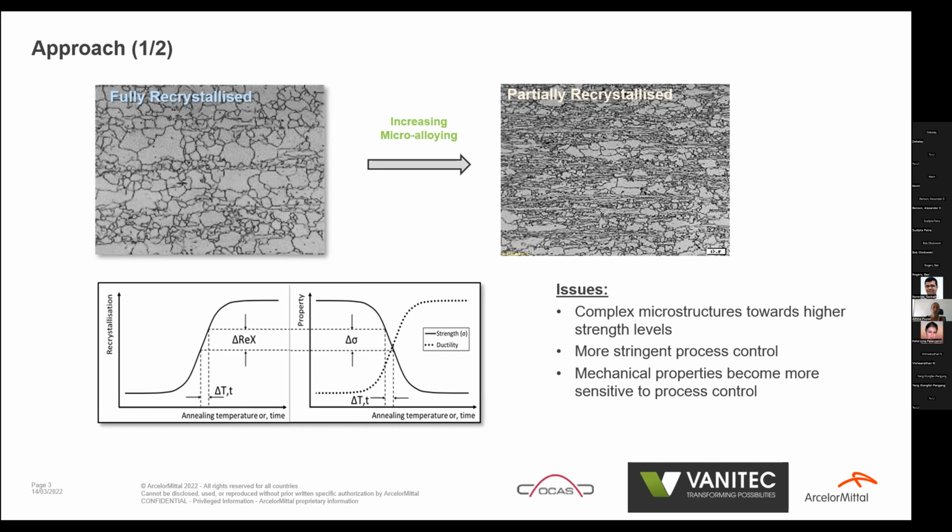Microalloying specifically delays recrystallization onset, and hence the resulting microstructures are partially recrystallized. However, the understanding of how this is linked with the process parameters and how stringent these must be in an industrial trial is what we are interested in, and that's what we want to study within this proposal.